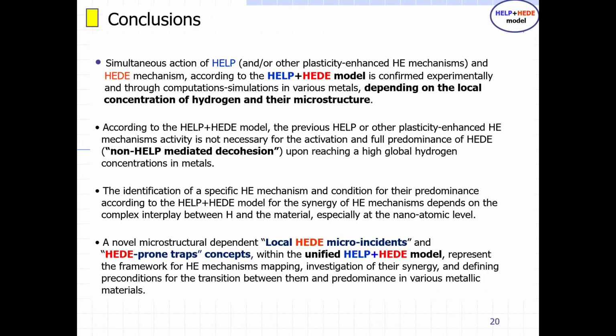So, some conclusions. I tried my best to give you an overview. It's a very complex topic, and I'm aware that it's not easy to present the results, but what's important is that we still don't have results which will finally confirm the hydrogen embrittlement mechanism. We need microstructure mapping techniques, atom probe tomography, and other techniques. We also published a paper with authors from Brazil and Austria, in which we pointed out that in order to solve the problem of hydrogen embrittlement, we need to confirm these hypotheses of mechanisms, because all these mechanisms, HELP and HEDE, are well known but still not confirmed at the required level.